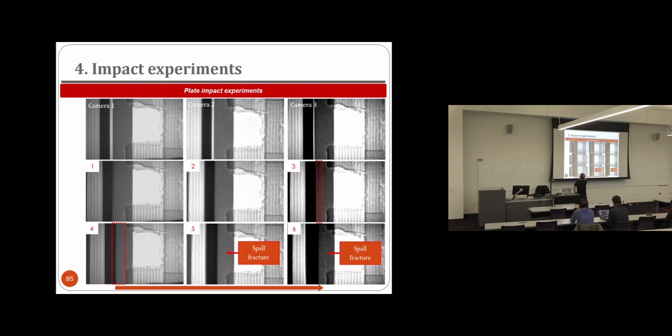So the projectile didn't reach the target yet. So it's coming. It's very close to impact. Okay, here is impacting. It is just right there. And now here you can start seeing, in the image that we have already processed you can see it better, that the pores disappear. Here the pores have already collapsed.